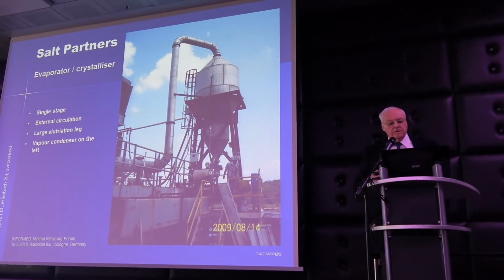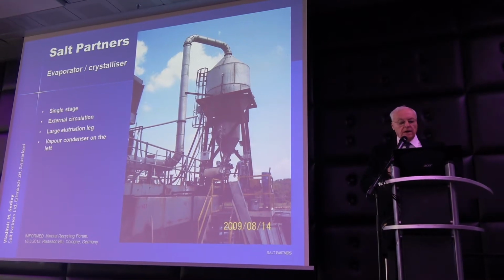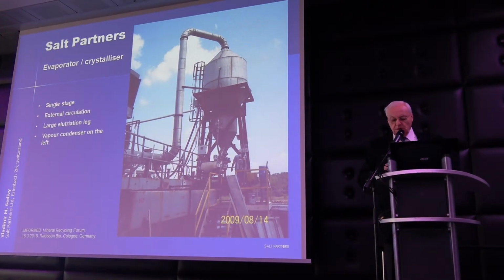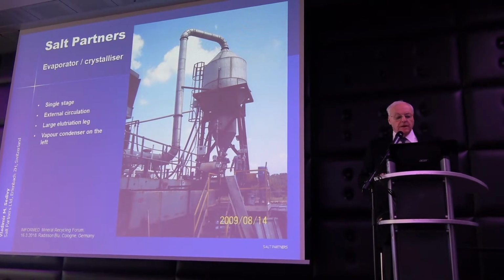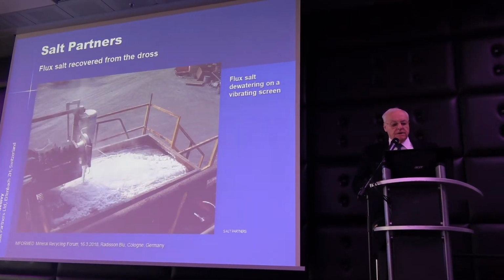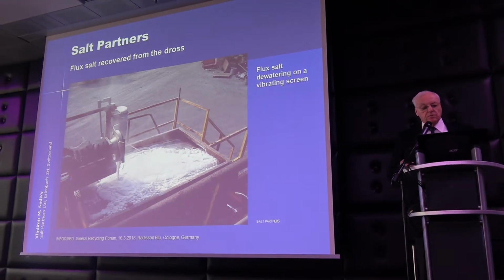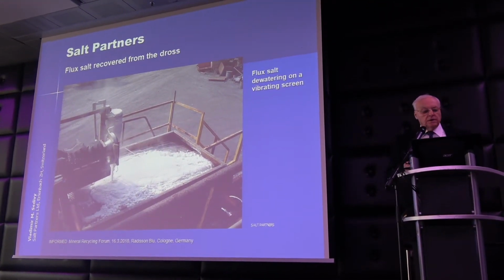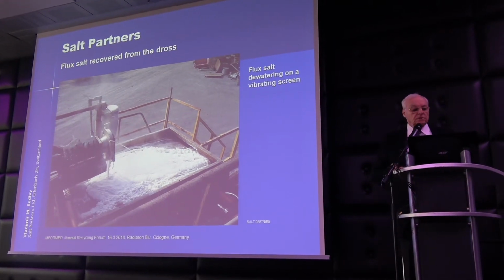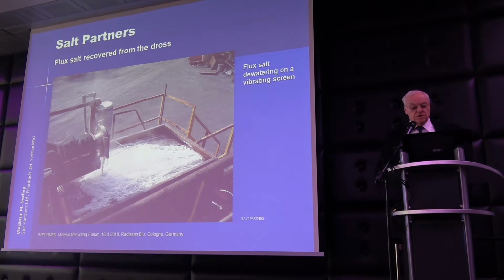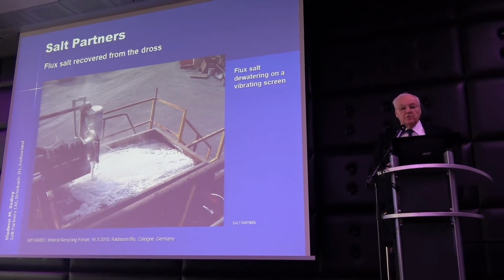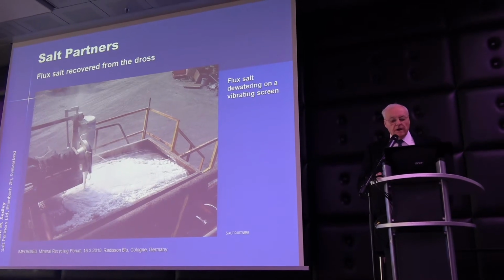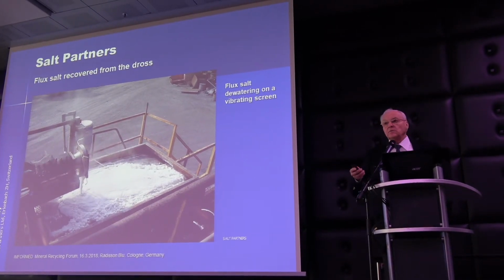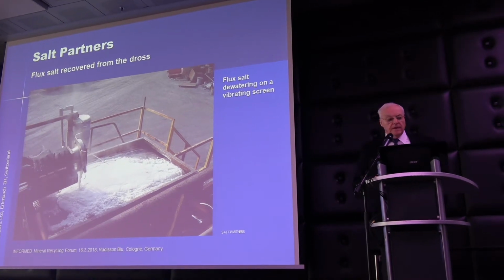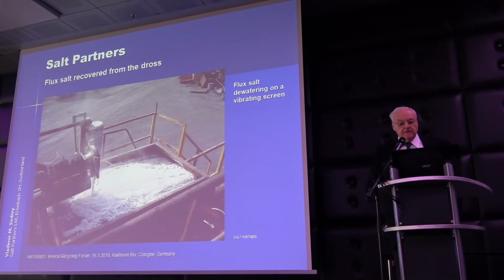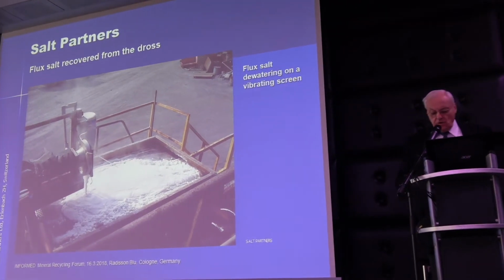Condensate is then fed to the steam generator, and steam is produced to heat the evaporation process. This is the outlet of the crystallized salt, sodium chloride and potassium chloride, on a vibrating screen. It was a very good decision, instead of using centrifuges here, to use this vibrating screen doing a partial dewatering, because the residual water evaporates immediately in the rotary oven.